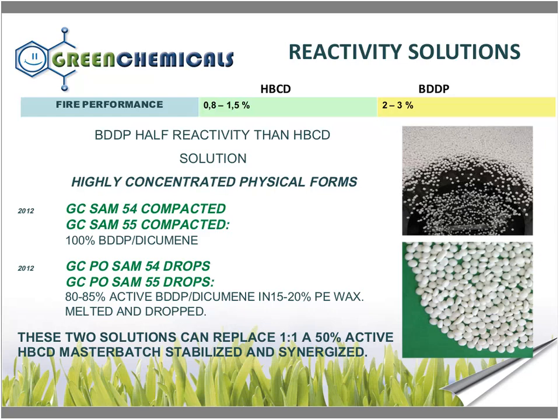So we came to a brand new technology, which we call drops, obtained using the low melting point of BDDP and dicumene. We put BDDP and dicumene in PE wax, melted everything together, and made it drip, cooling down the droplets we obtain. It is treated like a master batch. You can see it is completely dust-free, and we can arrive at up to 85% active BDDP and dicumene. Considering these two solutions, we can replace one-to-one the 50% active HBCD master batch, obviously stabilized and with synergies inside.